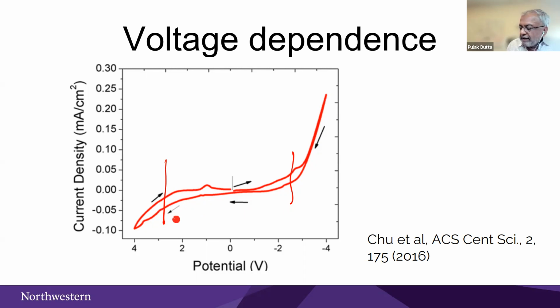So we studied the structure in this range, and it turns out that low voltages like 0.5 volt and high voltages like 2 point something are quite different. Again, that's not something you expect in aqueous solutions.